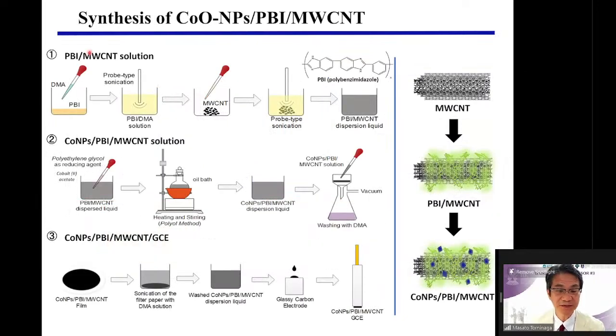So I synthesize cobalt nanoparticles. Okay, I would like to introduce this method briefly. I use multi-wall carbon nanotube. This surface is modified with PBI. PBI is a polymer, polybenzimidazole, like this polymer. The surface is covered with PBI because the PBI can disperse the multi-wall carbon nanotube well. Also, this PBI can fix the cobalt nanoparticles. After that, I synthesize cobalt nanoparticles on the multi-wall carbon nanotube surface by using this method.